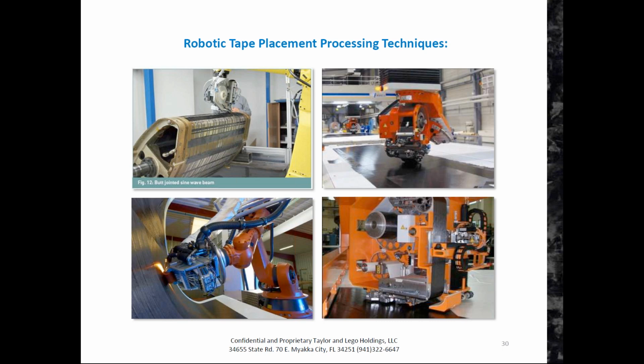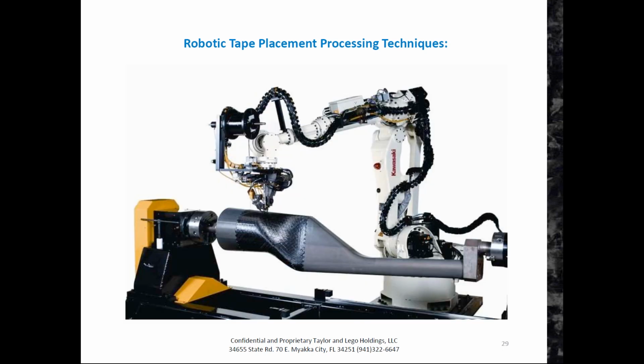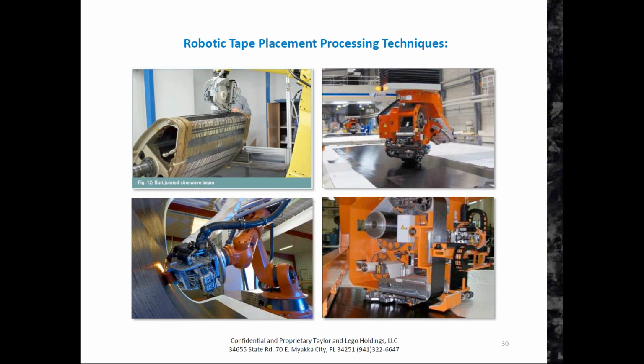Okay, so these are additional head units, very similar to what you see on the end of this robot. These are just bigger ones. These are all rotating mandrels for the most part. Well, take that back. This image right here is a rotating mandrel, so you can imagine that could be a wing structure. Right here, this is on a table, so it's actually doing a tape structure where you're controlling the orientation of the fiber. This is where it's doing a contoured shell on a mold that is angled at about 70 degrees.